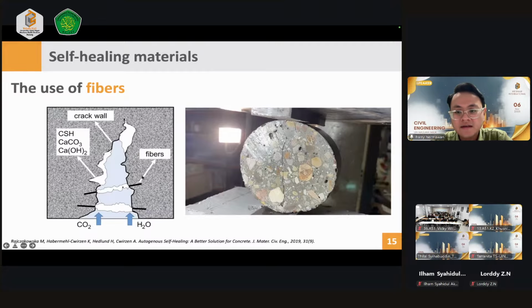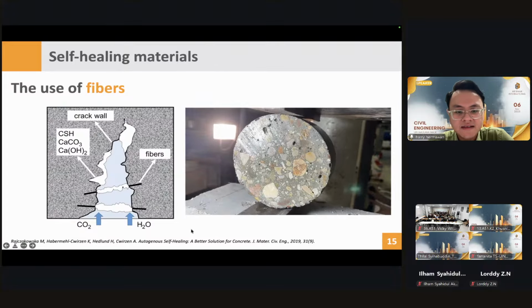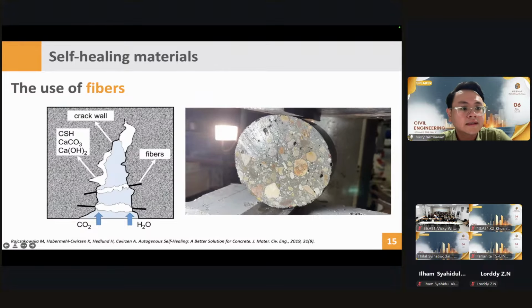And with the fibers, we can try to control this. Imagine if we have a crack and the water comes into the crack, so what's going on? There will be some hydration products forming on the surface of the cracks due to the chemical processes from the calcium carbonate precipitation or also from the ongoing cement hydrations. Okay, so the use of the fibers is beneficial to control the cracks.